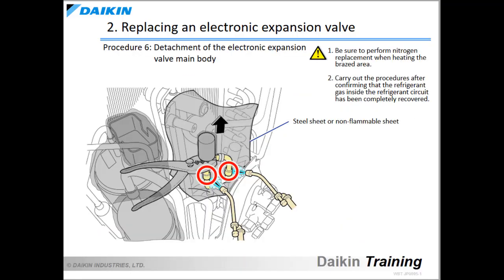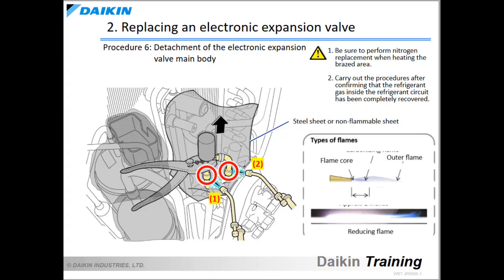Be sure to confirm that the refrigerant gas inside the refrigerant circuit has been completely recovered before heating the brazed area with a welding torch. Protect the components around the electronic expansion valve with non-flammable sheets for welding or steel sheets to prevent any damage from direct contact with the flame. While performing nitrogen replacement, heat the two brazed joints and detach the electronic expansion valve by pulling it out with pliers. Use the reducing flame. After the valve has been detached, replace it with a new one.